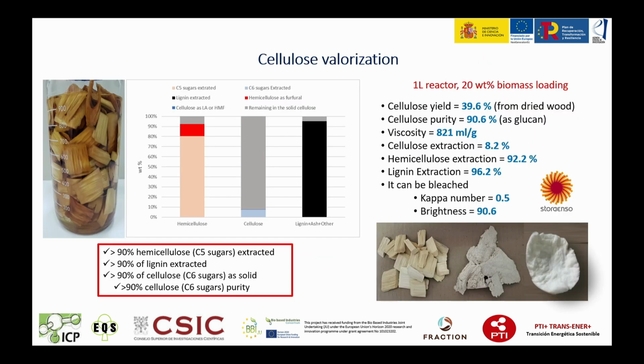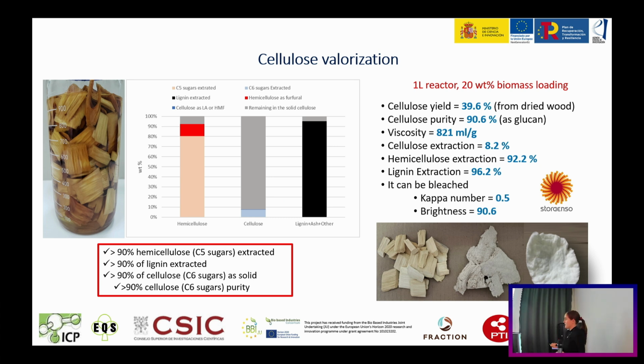So our objective is to extract 90% of the hemicellulose and lignin, and for this we put the biomass and the solvent solution in a batch reactor, and then we perform the reaction under their respective conditions. So as you can see, we obtain 40% of cellulose with high purity, and we have worked with Stora Enso to demonstrate that this cellulose can be bleached by conventional methods, obtaining a kappa number and brightness that indicate that this cellulose has the necessary quality to use it for the textile industry.